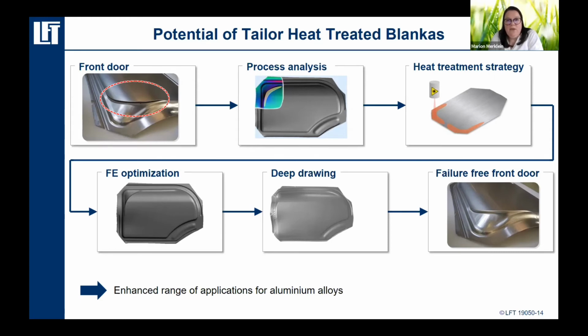As a consequence, we said, okay, we can do such a process analysis using finite element analysis, investigating where in reality the material flow has to come from, where the material flow stops first, and if we do so, we know which areas we have to locally heat treat in order to soften the material and to improve the material flow. On the one hand, you can follow such a process route in the virtual world, doing all of that by FE analysis. On the other hand, you can also do it in reality, because you can transfer the results coming from the FE analysis.